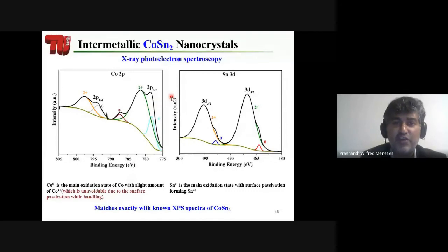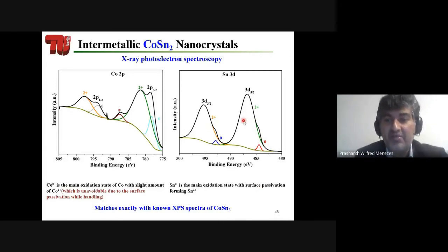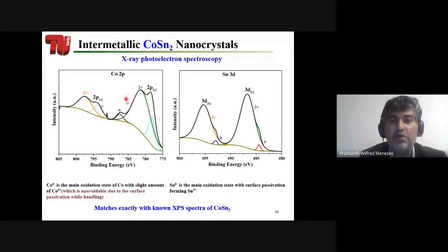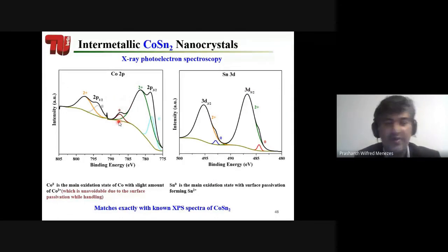And this is X-ray photoelectron spectroscopy. If you are not familiar with photoelectron spectroscopy, this is just to know the oxidation state of the material on the surface. That's it. So what you see here is that our material has a lot of cobalt zero, metallic cobalt, which we expect for our cobalt tin material, and also we have tin zero. That means our cobalt tin is an intermetallic with oxidation state close to zero and slight oxidation. This is due to the passivation.